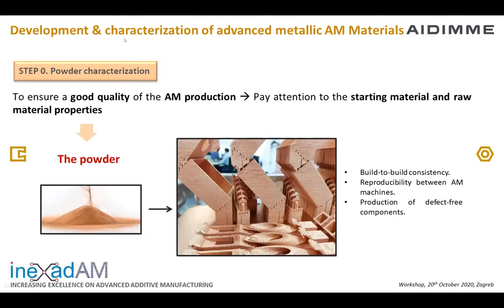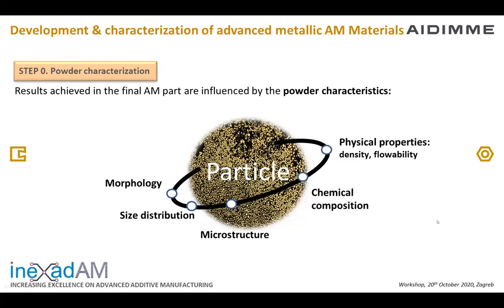We start with the powder characterization. It's very important in the additive manufacturing process, to ensure a good quality of the production, to pay attention to the starting material and the raw material properties, because the properties of the final part will depend on the powder, but also the build-to-build consistency and the reproducibility between different additive manufacturing machines, to achieve components free of defects. So results achieved in the final part are influenced by the following powder characteristics: morphology, size distribution, microstructure, chemical composition, and physical properties like density and flowability. I will explain each of them very briefly.